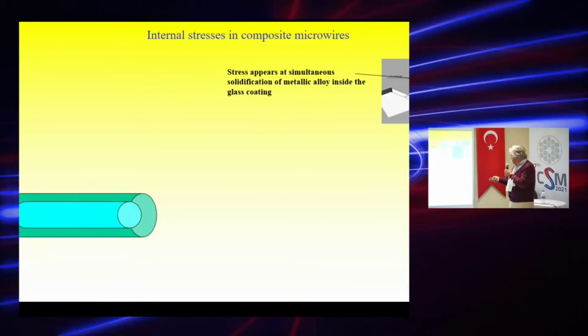And to understand this, this was my question to Larissa. We have to keep in mind that the materials have strong internal stresses. Once we cool metal and glass together, they have quite different thermal expansion coefficients. And this is a schematic picture of the fabrication. So once both glass and metal shrink, the metal is subjected to strong internal stresses, and this is the calculation.